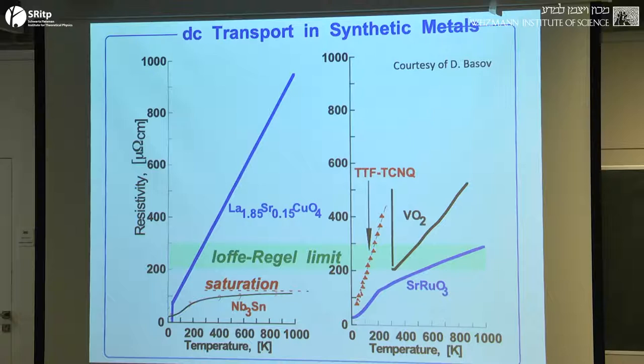People like to play around with just what the bound is on Boltzmann transport theory, putting in factors of 2 pi in order to try to make it seem that Boltzmann transport theory has a broader range. Here was my estimate of the quantum of resistance, but whichever version of this you use, this resistance clearly marches up to values that are much above this Boltzmann transport limit. If I were to show you the resistance in the C direction, this is the resistance in the most conducting direction. If I show you for the same material the resistance in the least conducting C direction, it's still linear in temperature, but it's 2 to 3 orders of magnitude larger than this.